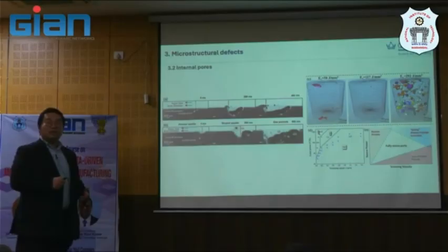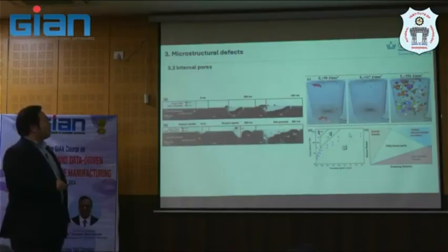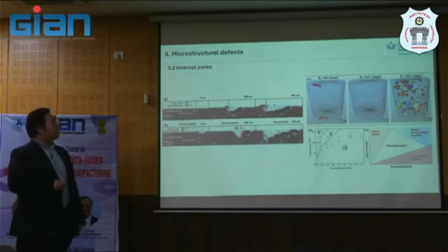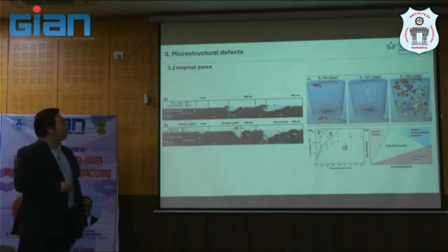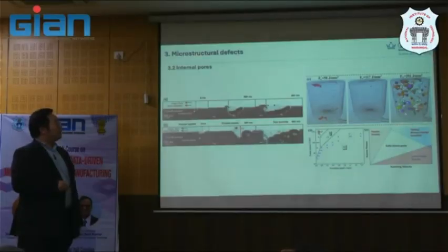I will talk to you more in one example of how they classify the defect during the printing in a more systematic way using data-driven approaches in the next topic. You see, this is lack of fusion, but this is more like process-induced porosity. It's more spherical, rounded. And if you choose the process parameter correctly, this will be a kind of minimum defect that you will see and form. And then that's why normally P and V, which is power and velocity, and you can identify some keyhole, probably this is related to keyhole porosity, this related to lack of fusion porosity, and this is somewhere in the middle.